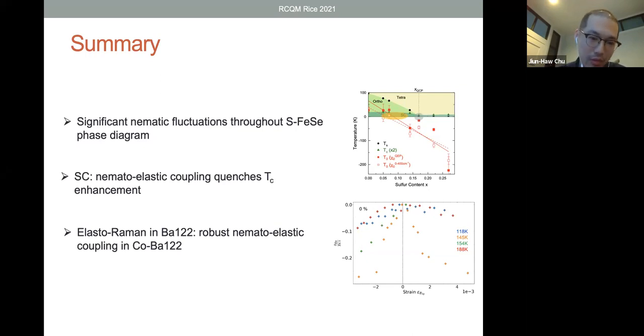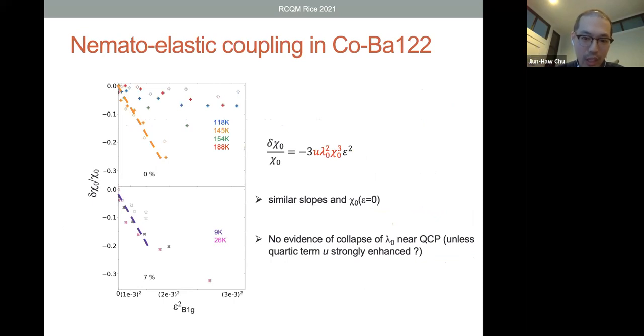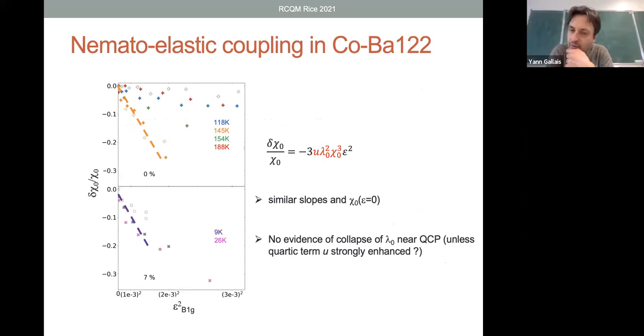As you know, we have a recent work on using strain to suppress superconductivity. One of the puzzling things we want to know is whether the strain actually suppresses nematic fluctuations. But at least from your data, it looks like it is the case. Yeah, and what is quite striking also is that the suppression seems to be almost identical right above TC and well below TC. I see.